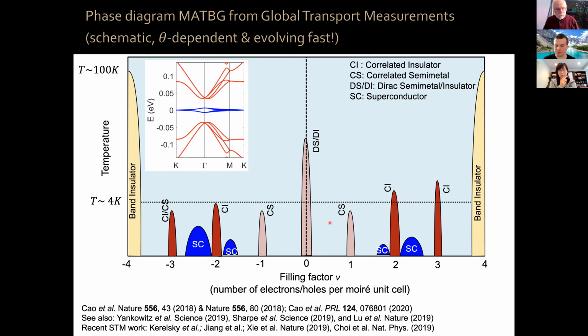The situation can be complex. Let me not focus too much on that. When you dope electrons or holes around those correlated insulator states, you have superconducting domes. The most robust is this one, the second most robust is this one, and these others are seen depending on the device quality, the type of device, the twist angle, etc. So this is what our understanding was of the system based on global electronic transport measurements.